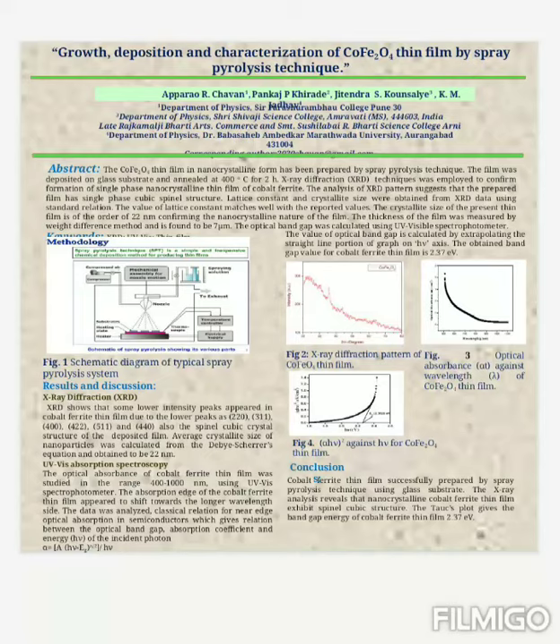The peaks are 220, 311, 400, 422, 511 and 440, also showing the spinel cubic structure of the deposited film. But see in this figure, the 311 peak is a high intensity peak as compared to other peaks. The average crystalline size of nanoparticles was calculated by the Debye-Scherrer equation, and the average crystalline size was obtained as 22 nanometers from the XRD patterns.